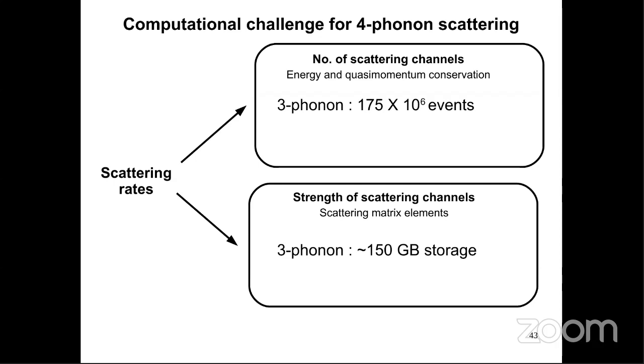You typically have about 100 million scattering events of 3 phonon processes, and to calculate and store the strength of these events, you typically require 150 gigabytes of storage. These kinds of numbers are very doable these days. You can get this work done on a single compute node in a matter of a couple of hours.